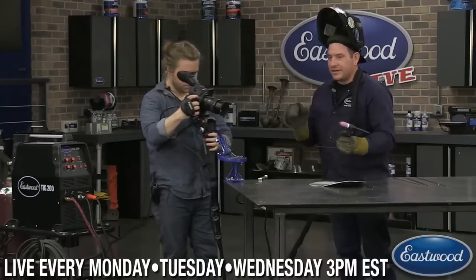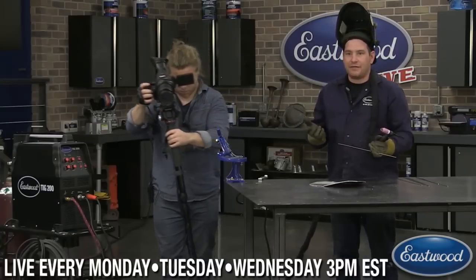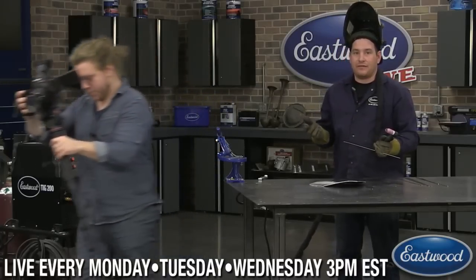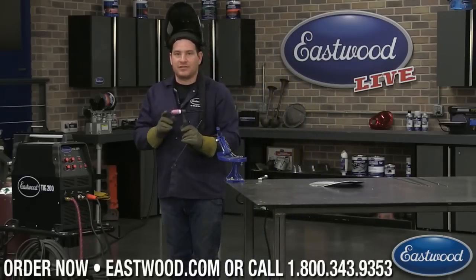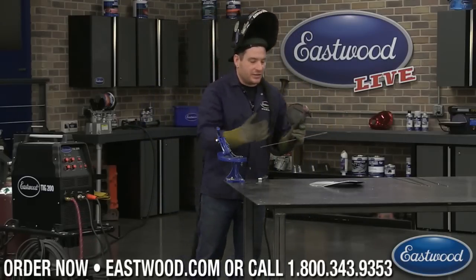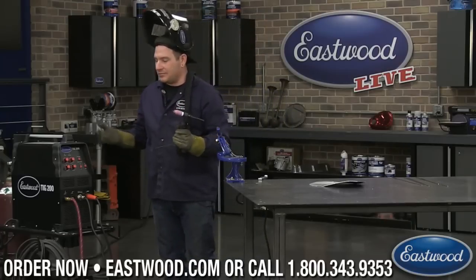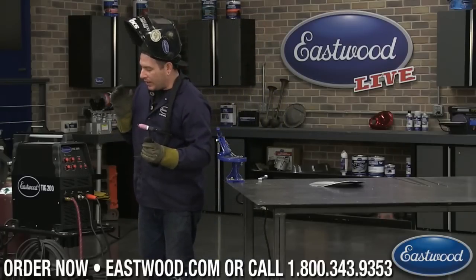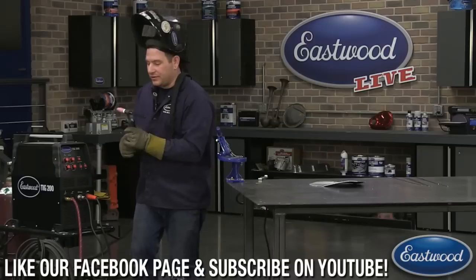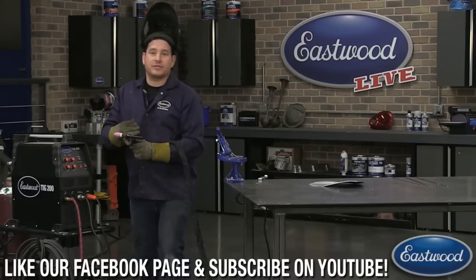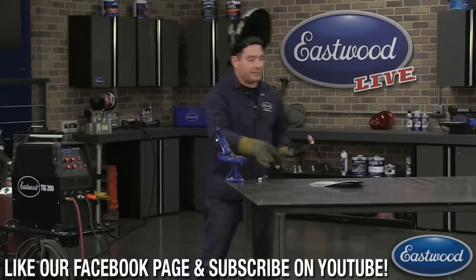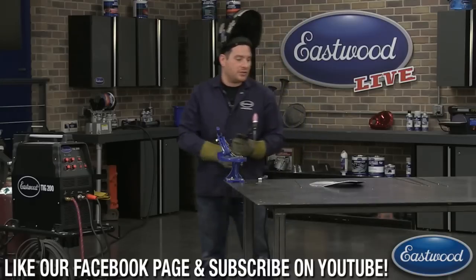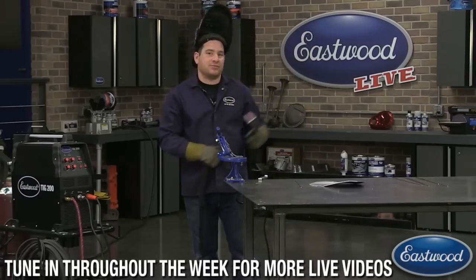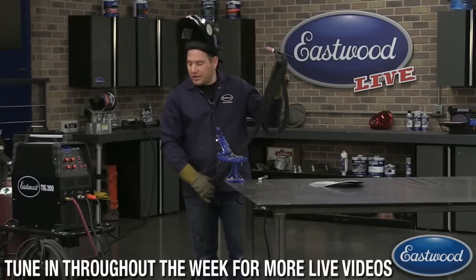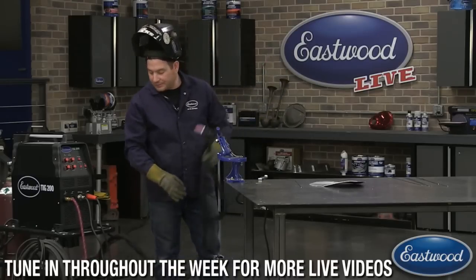Now, all we did was we were at negative half, and it went to positive half. So we went just one setting up, and that's the difference that it made from doing a half decent stable weld to something that you can't even work on. I see that far too often where beginners have their machine, they don't pay enough attention to the clearance effect or the balance control, and they're sending us photos like that thinking there's a problem with the welder, and it's just a little tweak of your settings and you're ready to go.